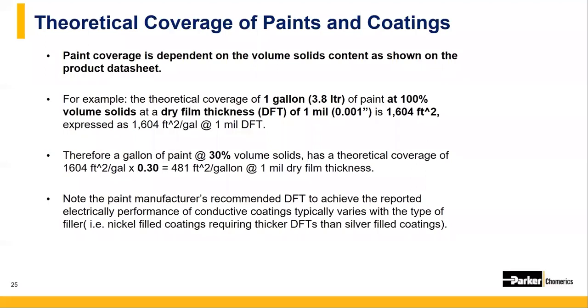The best way to compare the cost of conductive coatings is by calculating the applied cost of each material. To figure out the cost of material for each of your parts, you must take into consideration the price per gallon of the coating, the area of the part that you're painting in feet squared, and the manufacturer's recommended dry film thickness, DFT, to achieve the coating's mechanical and electrical performance. Theoretical coverage of conductive coating assumes a full gallon, which is not always the case, so take that into account. Then you should estimate overspray and material scrap for conductive coating during application as well. Some people just add a percent, 5-10% scrap.